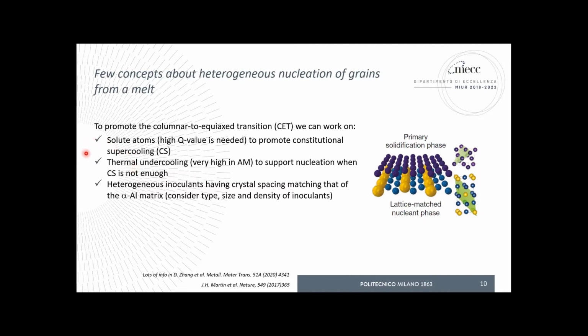in laser-based additive manufacturing, thermal undercooling is also very important, and it is very high, and it can also support very much the heterogeneous nucleation, or the growth of the solid matrix from a nuclei. And then, of course, goes without saying that we need to consider the inoculants, a specific type of inoculants, having a specific crystal spacing matching that of the aluminum matrix. Again, I'm trying to see on a more macroscopic perspective the issues that Maria Teresa was talking about before my talk. And so we shall consider the chemistry, the crystal structure, but also the size of the particles themselves, and the density, the volume fraction of these inoculants.